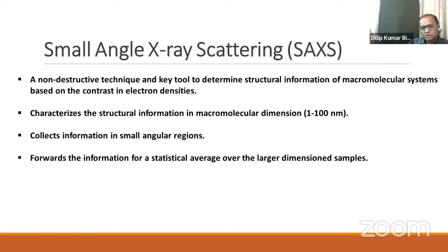It may give only a rough idea, because statistical averaging with only one image at one spot of the sample may give wrong information about the grain size and crystallite size. But in the case of X-ray scattering, what happens? If you irradiate the sample with the X-ray beam, the whole sample is exposed. So whatever information you collect in terms of intensity is much better about the structure as far as statistical averaging is concerned, and this is very much essential for research work. Research needs that kind of accuracy, which is never achieved with an electron microscope, be it scanning or transmission.